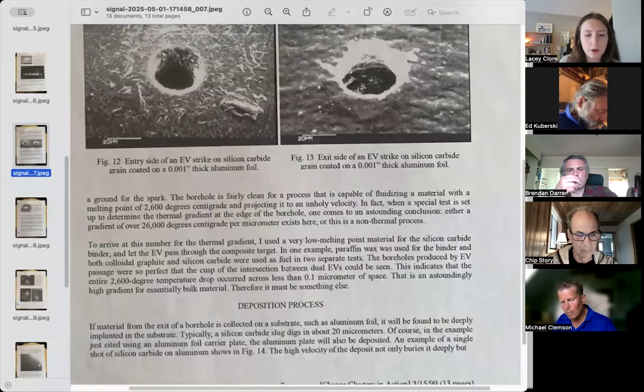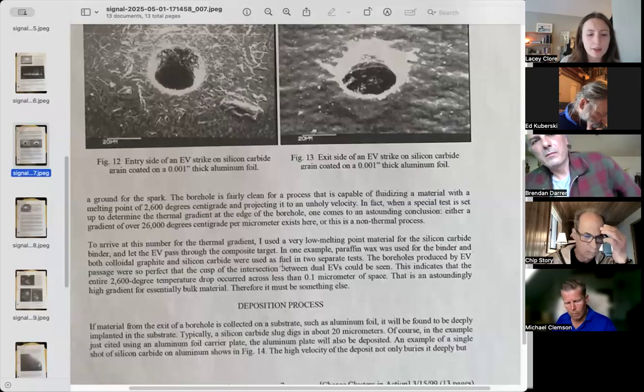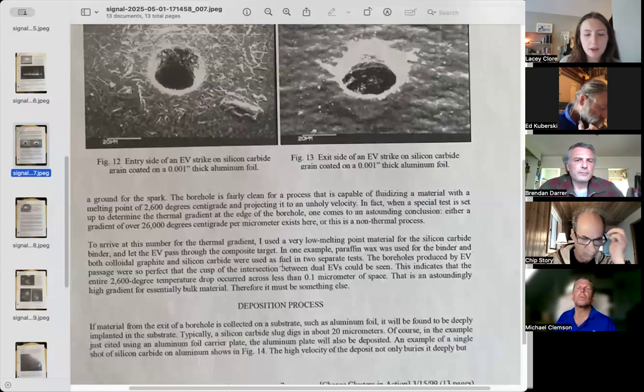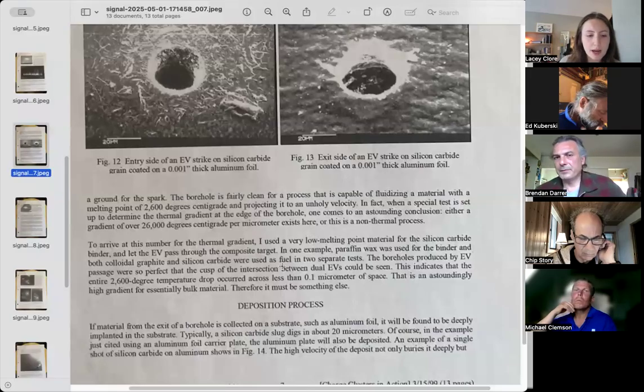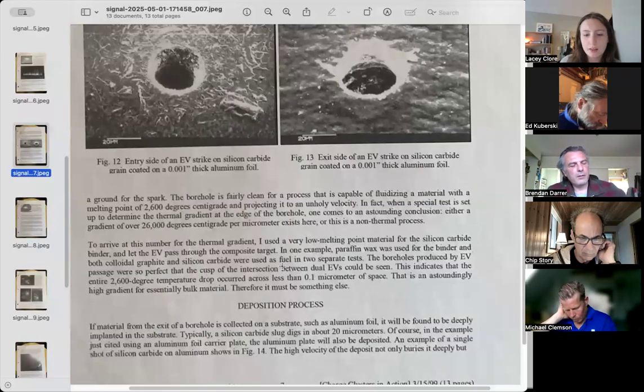To arrive at this number for the thermal gradient, I used a very low melting point material for the silicon carbide binder and let the EV pass through the composite target. In one example, paraffin wax was used for the binder, and both colloidal graphite and silicon carbide were used as fuel in two separate tests. The boreholes produced by EV passage were so perfect that the cusp of the intersection between dual EVs could be seen. This indicates that the entire 2,600 degree temperature drop occurred in less than 0.1 micrometer of space. That is an astoundingly high gradient for essentially bulk material. Therefore, it must be something else.